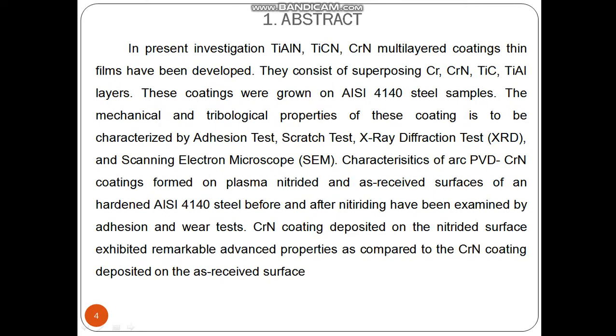Characteristics of an arc PVD CrN coating formed on plasma nitrided and as received surfaces of hardened AISI 4140 steel, before and after nitriding, have been examined by the adhesion and the wear tests. The CrN coating deposited on the nitrided surface exhibited remarkably advanced properties as compared to the CrN coating deposited on the as received surface.